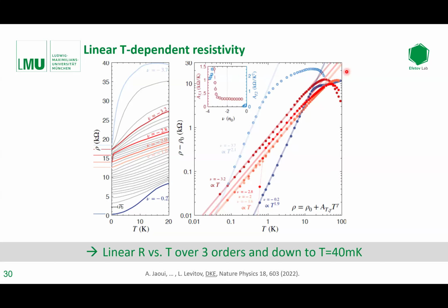This has been worked out in a paper by Andrea Young early on: this drop in resistance we understand as a population of the dispersive bands. So there's a second conduction channel populated with much higher mobility electrons, which lowers the resistance.